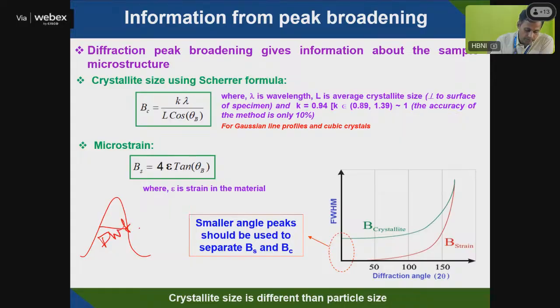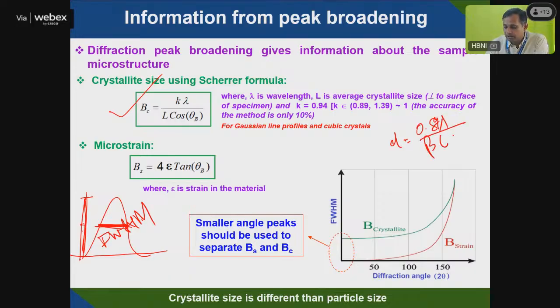This is nothing but FWHM, full width at half maxima. This is your peak, this is the maximum peak height, and the full width is measured at half of that height. So you have to find the peak intensity at half maximum and its width. Then, using the Scherrer formula, you calculate beta, and the particle size D equals 0.89 lambda by beta cos theta. K is taken as 0.89, generally assuming spherical particles. So you can calculate the particle size using this equation. You can calculate strain using 4 epsilon tan theta.